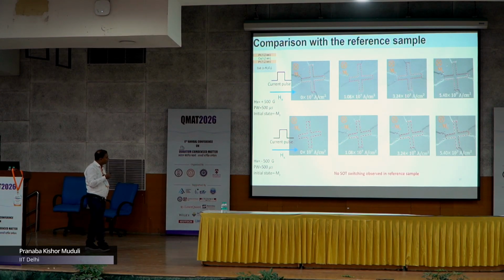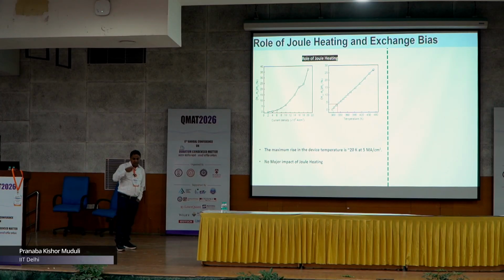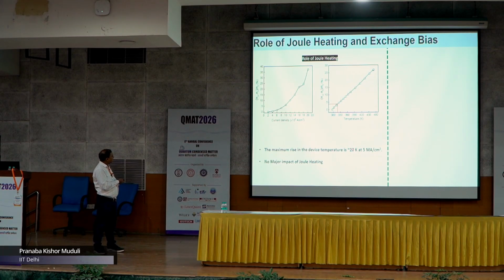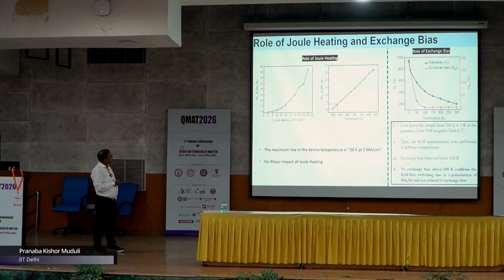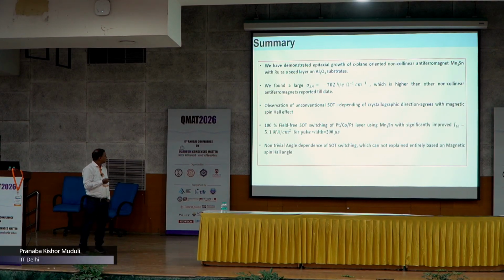In order to check that this is not due to any heating effect, we did a lot of control experiments. The first control experiment is that we did this experiment without any Mn3Sn, and in this case we do not see any SOT switching, indicating that the switching we observed was due to the Mn3Sn. But you may still say that maybe there is some heating and that the heating is driving this. So we also checked the heating, and the estimated heating is around 20 Kelvin, which is not that high, so heating cannot drive the switching. Also we saw the field polarity dependence, which cannot be explained simply by heating. We also checked that because this is an antiferromagnet, there can be some exchange bias, and this exchange bias may also be responsible for field-free switching. In fact, we could measure the exchange bias at low temperature, but at room temperature there is no exchange bias. So this cannot explain the switching, indicating that we can explain our observation more or less using the magnetic spin Hall effect.